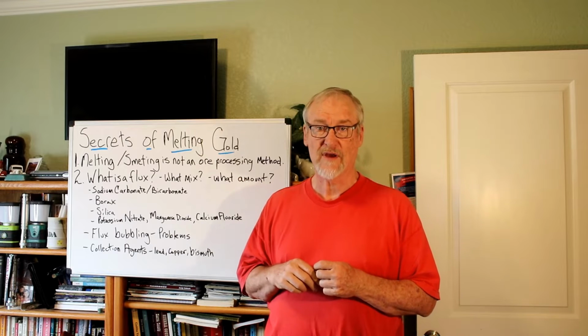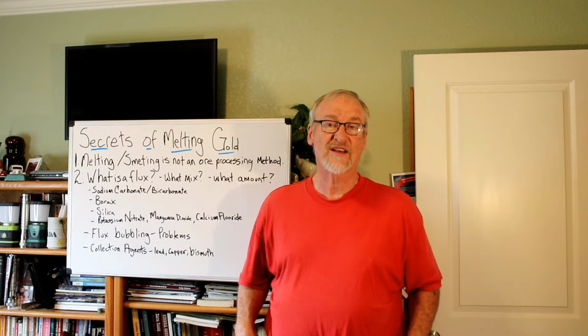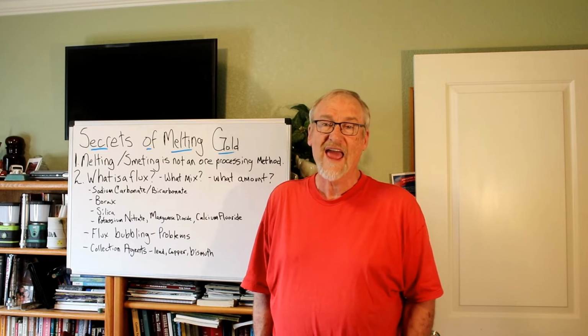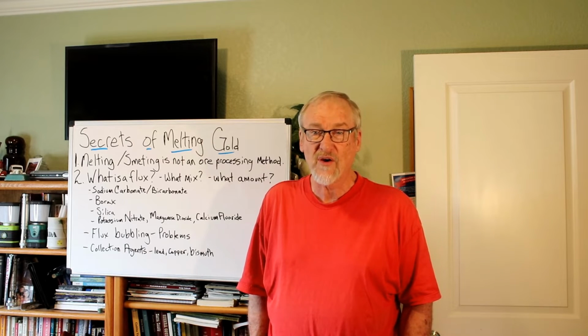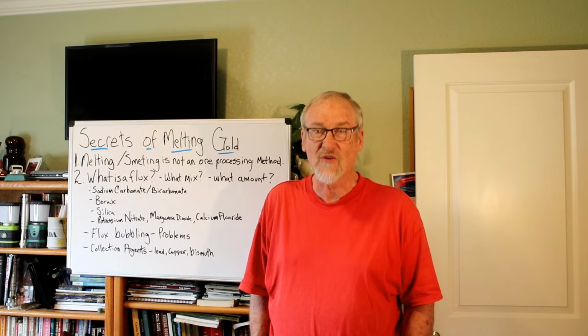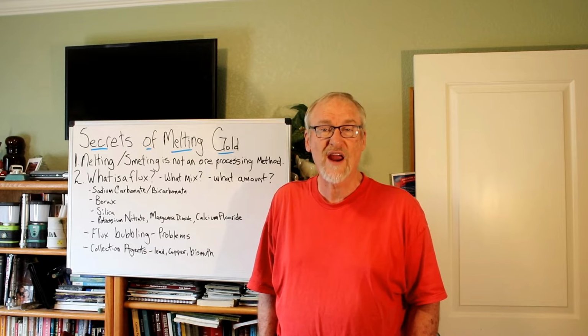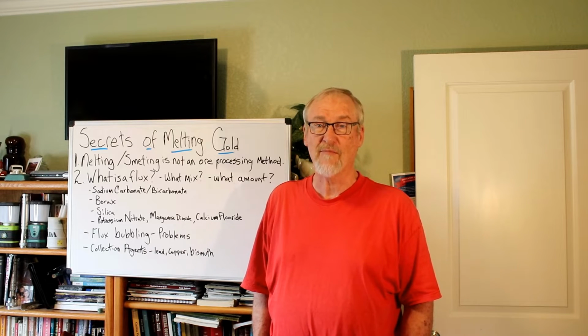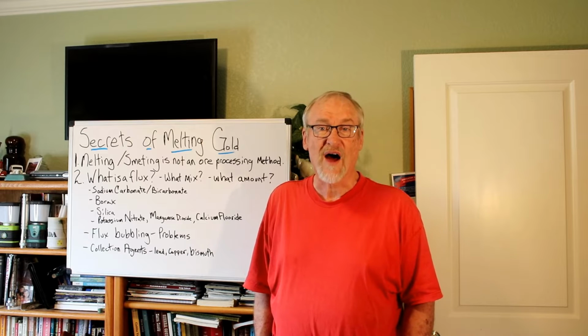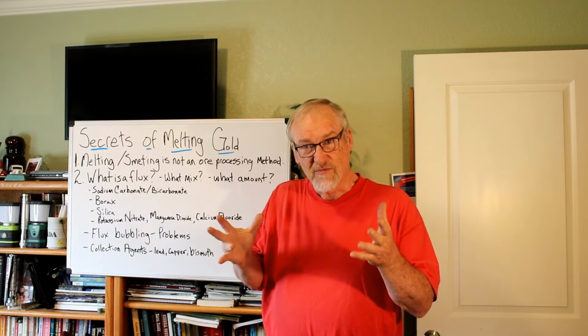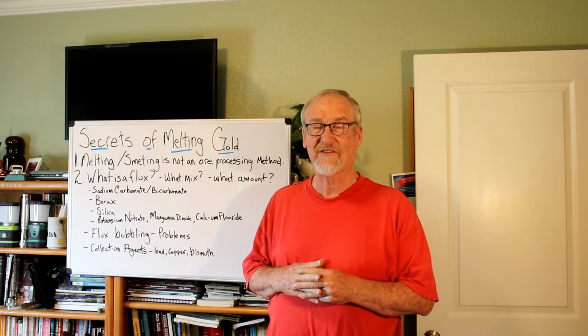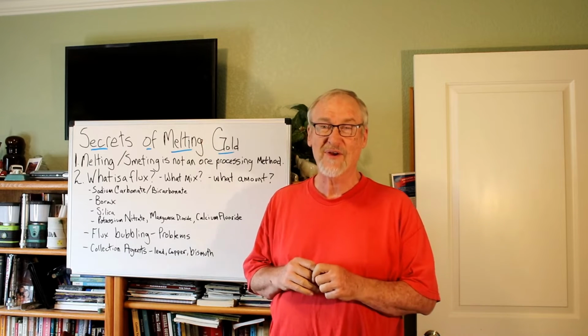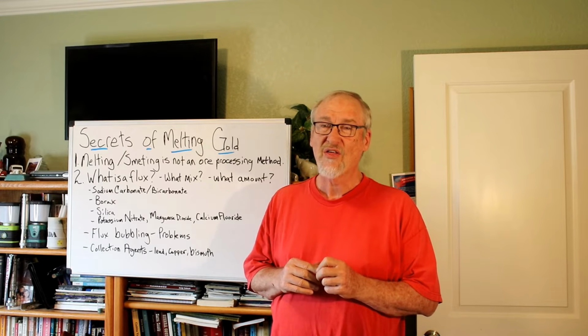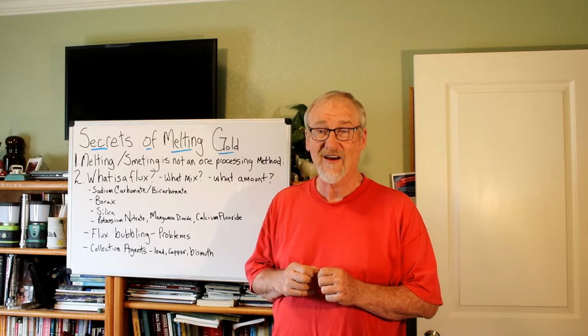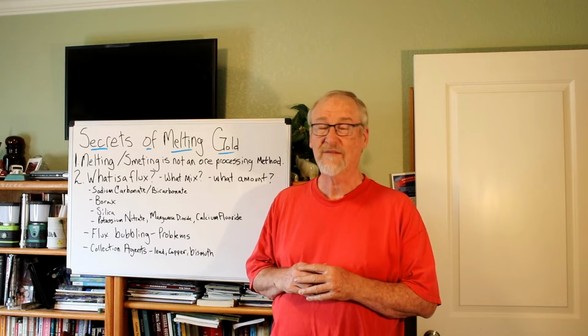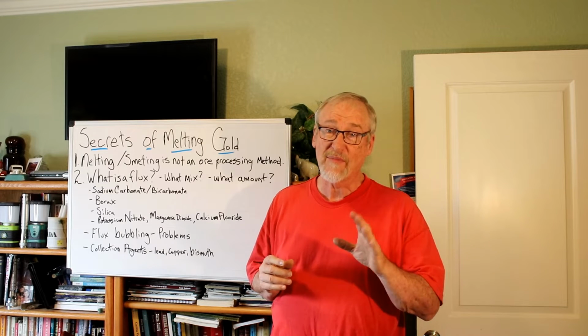Anyway, what amount? So I've seen guys who are doing electronics recovery, and they've purified the gold, and they've gotten it real pure, and it's not any junk with it, and they may put just a sprinkle, a pinch of borax when they melt a several gram little button of gold. And so if you have very little impurities, then you need very little flux. If you have a moderate amount of impurities, you might need 3 or 4 times the weight of your gold or your anticipated gold.